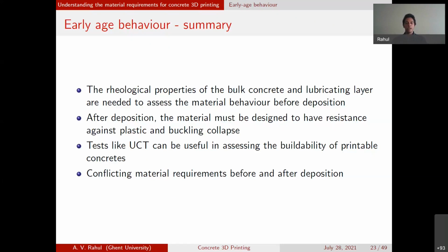rather very fast. To address this conflicting requirement, one of the ways is to introduce an accelerator at the nozzle, with a small mixing unit at the nozzle. This is also being used by several research groups now. The accelerator introduced at the nozzle causes a very rapid evolution of elastic modulus and yield stress, allowing you to make relatively larger structures at much faster print speeds.